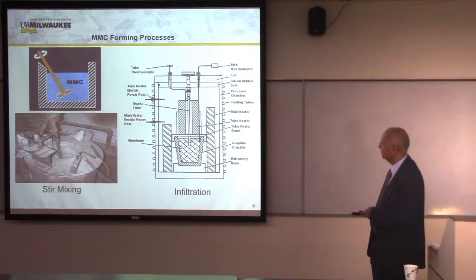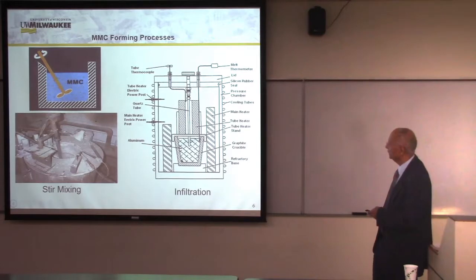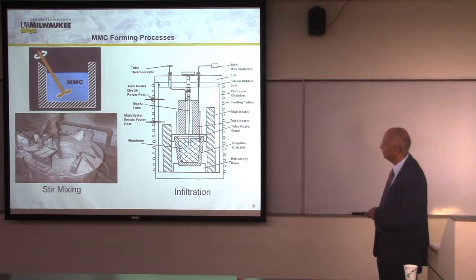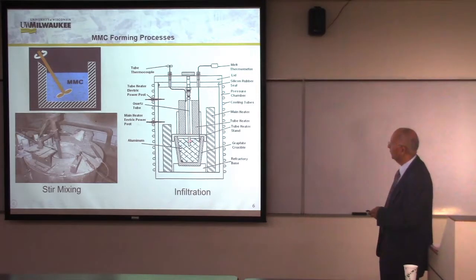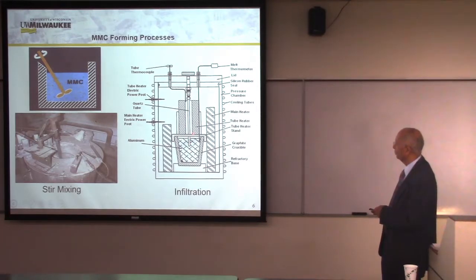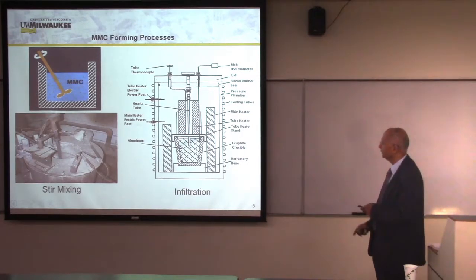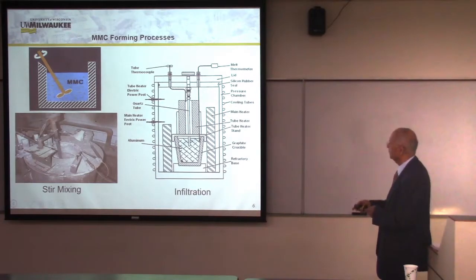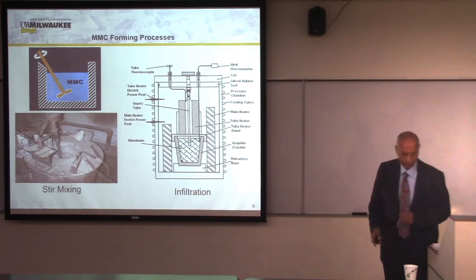The other method of producing high volume percentage reinforced metal matrix composites is where you put a loose bed or a preform of ceramic particles and then infiltrate it with liquid metal from below or from the top. From below, it is very much like low pressure die casting. The liquid metal infiltrates the spaces between the particles and it solidifies to produce metal matrix composite castings.